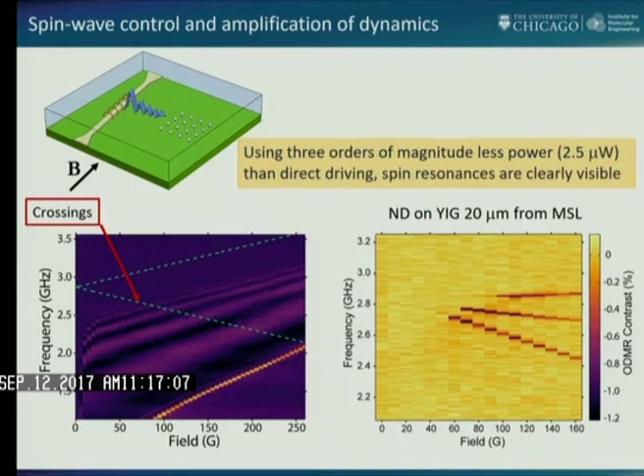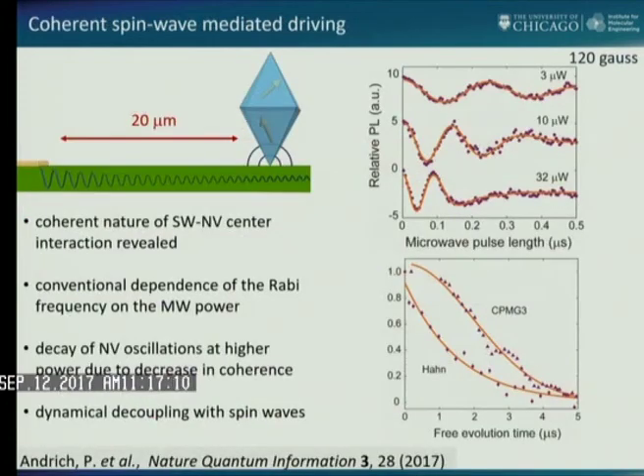So again, that worked pretty well. And as is often the case with faculty members, who usually assume the student is incorrect, right? As it turns out, of course, the student was completely correct. And he discovered something really fascinating, which is that you could couple spin waves to these quantum states with relatively little loss of information. If you have an antenna and you have a quantum state, the field drops off as 1 over the distance. The farther you are from the antenna, the lower the signal, right? That's how antennas work. Putting this magnetic material nearby had no drop in signal. You could launch your signal here, the spin wave would carry it a very long distance, and it would be just fine with virtually no loss.